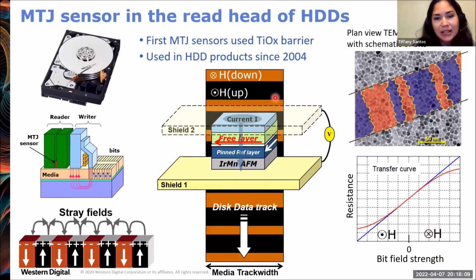And that's shown schematically here. We have the up and down orientation in the orange and the black colors here in the plane of the slide. And this is the magnetic tunnel junction here, with the white layers is the tunnel barrier, the free layer on the top, and a pinned reference layer on the bottom, and the current passes perpendicularly through the layers. The free layer can cant its magnetization as it senses the stray fields coming from the bits, and that corresponds to the resistance change here.